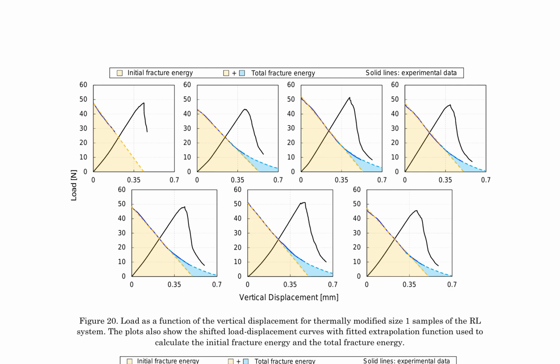Thermally modified wood exhibits distinct fracture behavior, particularly in the radial-longitudinal (RL) system. Researchers conducted fracture tests on two specimen sizes, observing stable crack propagation with load softening in all cases. Load displacement curves for small and large size samples are presented in figures 20 and 21, respectively, including shifted curves with fitted extrapolation functions for calculating initial and total fracture energies.